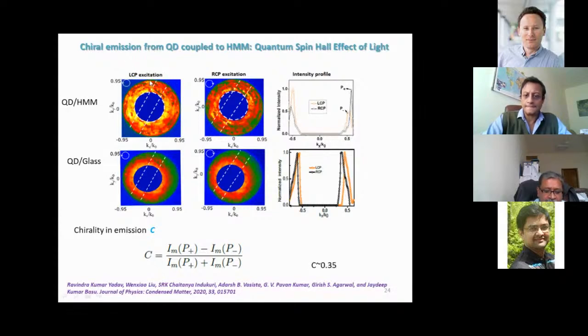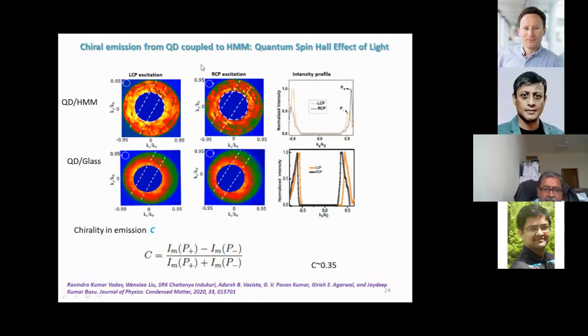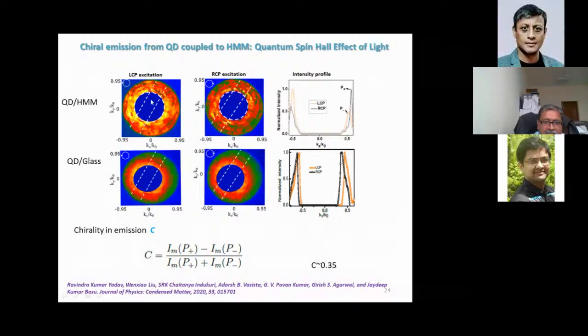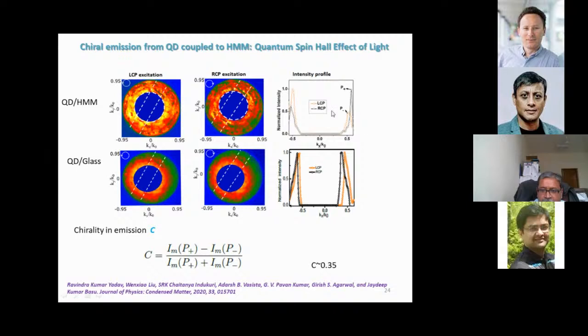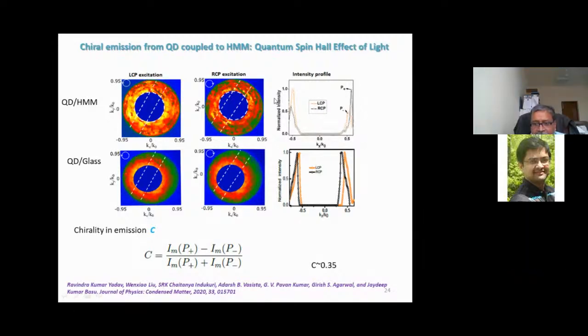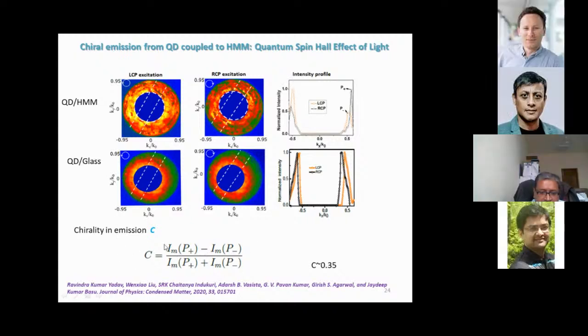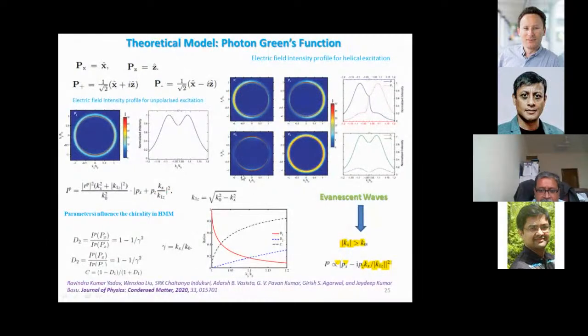So when you now come in with chiral excitation, you see a very strong helicity selection. Depending on whether you have left or right circularly polarized excitation, you see a preferential propagation in a particular direction, and you can pull out a chirality of the emission. And this was modeled. I'm not going to detail it because we have run out of time.